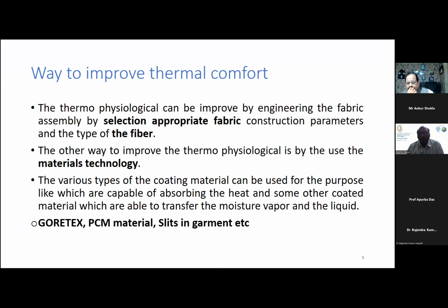Out of this, in order to improve the thermal comfort, thermophysiological comfort can be improved by selection of proper fabric constructions. That can be by changing the cover factor or GSM of the fabric, or a proper finish on the surface, or even operations like singeing, where burning out of protruded fibers will alter thermal comfort. It also depends upon the type of fiber. Wool fabrics are used in very cold regions; wool will absorb moisture and release latent heat. In some cases air permeability is more important, and in places like sportswear, wicking is more important. So these are the three major areas related to this.